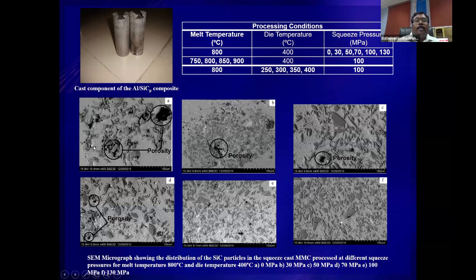This may be because of the solidification nature that pushes the particles to the front and you get agglomeration. But when you increase the squeeze pressure and also keep a 400 degrees centigrade die temperature and an 800 degree melt temperature, you could see that a homogeneous distribution was possible with 70 MPa, 100 MPa and 130 MPa pressure. I could see homogeneous distribution. That means the moment solidification starts, the melt disengages from the solid, that means the die.